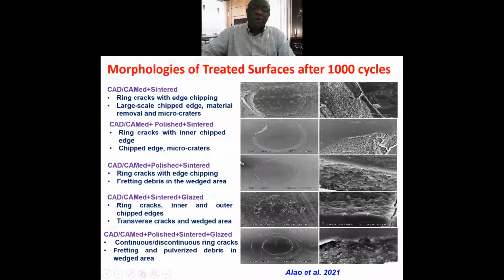For the CAD-CAM sintered polish, you can see the ring cracks with edge chipping, then fretting debris in the wedged area. CAD-CAM sintered glaze, you can see ring cracks with inner and outer chipped edges. Then you can see a transverse crack coming within the ring cracks. So that's called a transverse crack in the wedged area. Then for the CAD-CAM polished sintered glaze, you can see the ring cracks. You can see the continuous and discontinuous ring cracks and the fretting and pulverized debris in the wedged area.